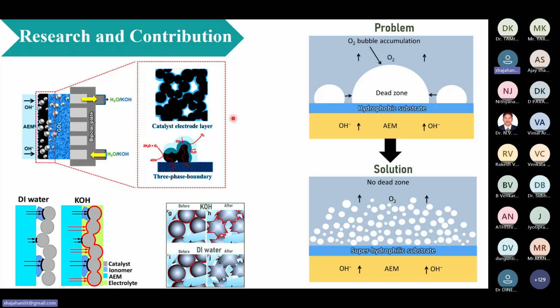Then what is happening? Due to the hydrophobic nature of the substrate, bubble accumulation regions form on the surface of the catalyst layer, creating dead zones. They degrade the catalyst, build up pressure, and obstruct the active sites. The exposure of active sites also gets obstructed due to these bubble regions. That is the reason it directly impacts electrolyzer performance, because these dead zones can damage the membrane and catalyst layer.